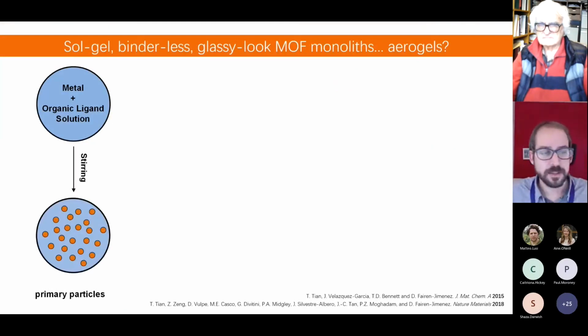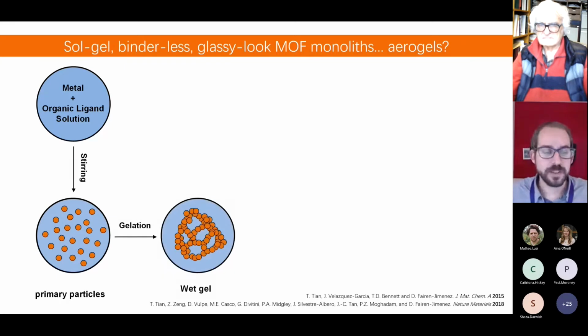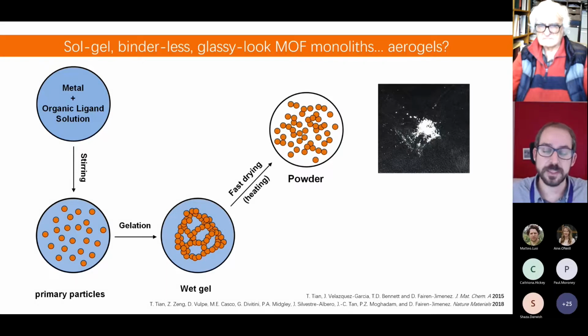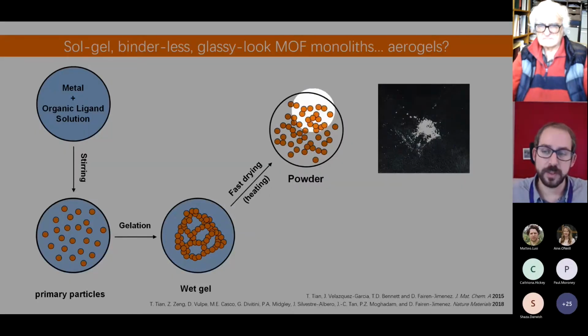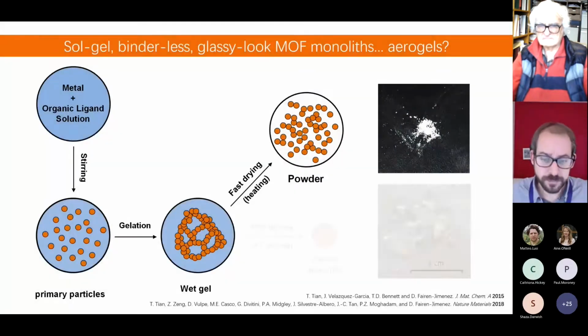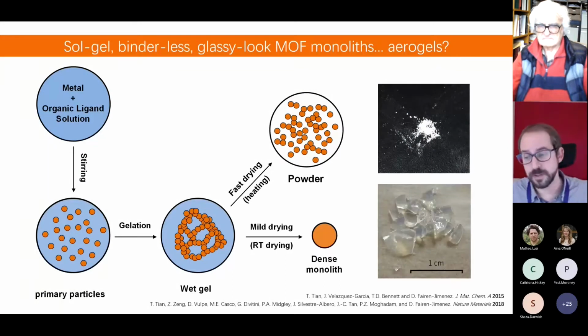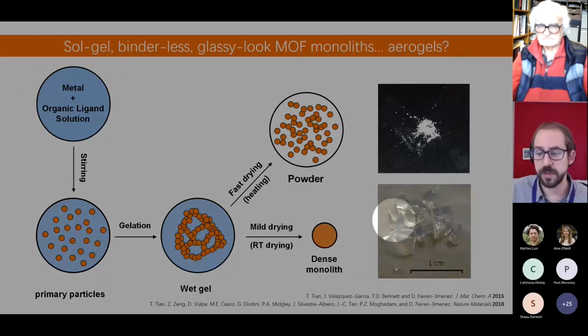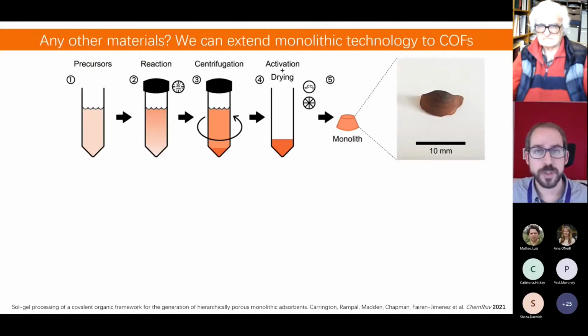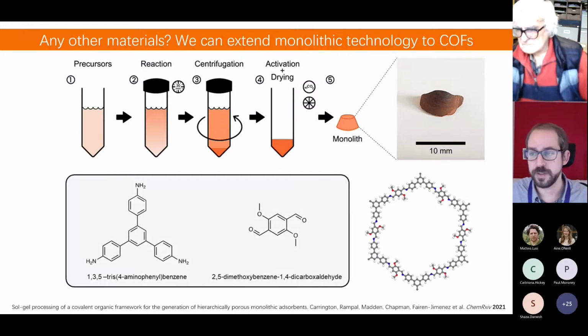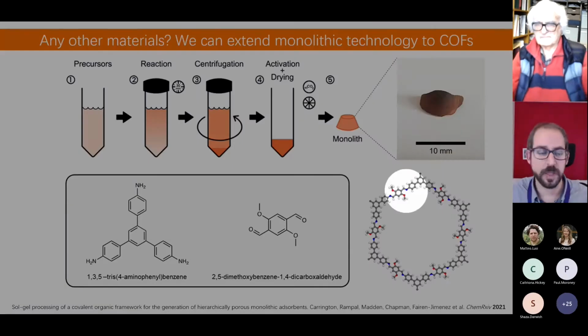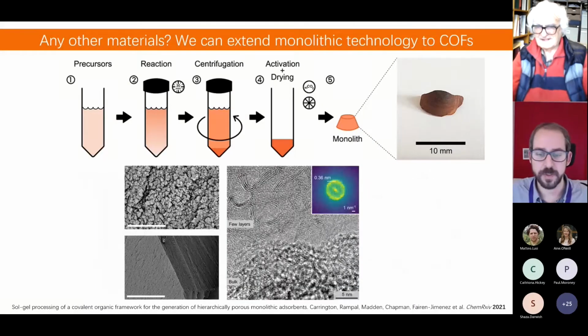The idea is that we have the synthesis of some primary particles, we have a gelation process to synthesize the material, and if we dry this very quickly, we end up with a powder. But if we have very mild drying conditions, we will end up with these very dense monoliths that you can really see here on the right. And we have been able to extend this to any MOF that we have been working with. We can also use this with covalent organic frameworks, and we can create some macrostructures out of all these different materials.